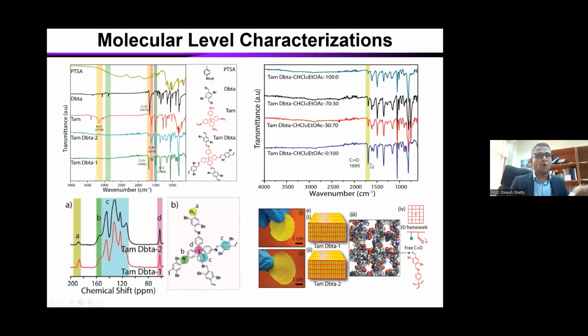Then we did a more detailed study to understand how this works by slowly increasing the amount of chloroform introduced into the system, and again we observed a similar trend. And we did solid state NMR studies to understand. As you can see, in the case of the defect system, you have almost an area under the curve of 1:1, corresponding to the imine carbon to carbonyl carbon. But on the other hand, in the less defect system, you have 1:0.1, which again suggests that in one system we have more free exposed carbonyl groups, which means defects.